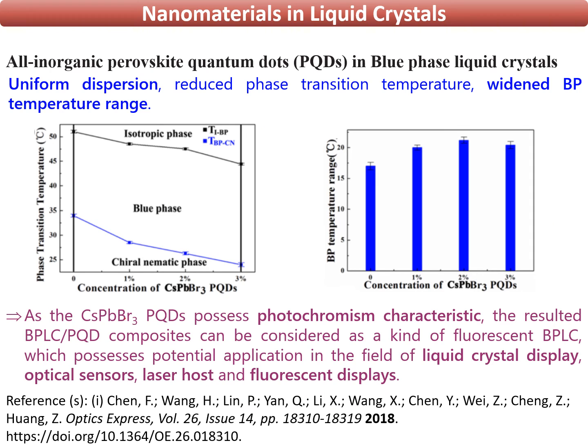This is the example in which all-inorganic perovskite quantum dots have been treated with blue phase liquid crystals. As can be seen from the figures on the left hand side and right hand side, in both cases, they have treated cesium lead bromide perovskite quantum dots with blue phase liquid crystals, and they have found that in all the cases, the liquid crystalline phase range is increasing, as can be seen from this figure.